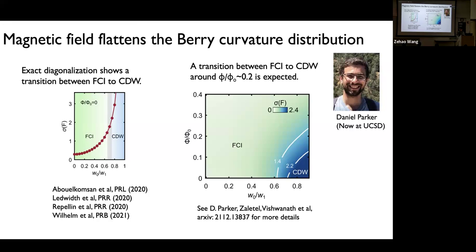Basically, you look at what's the Berry curvature distribution as a function of magnetic field. And then because, as was mentioned yesterday, this tunneling parameter is not quite known, we can only say this is the range. But the good thing is, it looks like the calculation is not too sensitive to the exact value. And then if you are generous and say it's between 0.6 something to 0.7 something, then the range you will get, going from CDW to FCI, is around 0.2 flux quanta, and converted to magnetic field is around 5 Tesla.